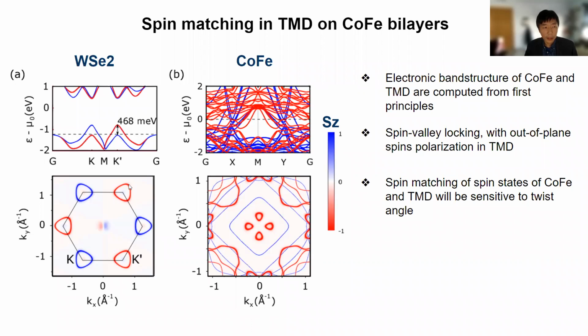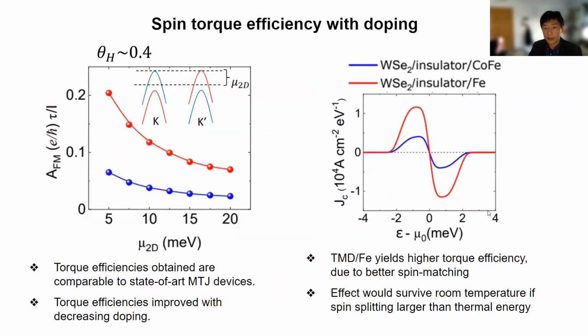And this is the Fermi surface of this TMD, and you can see that indeed the kappa and kappa prime valleys have opposite spin. So here is the band structure of the cobalt iron. We see that the Fermi surface of this cobalt iron is very different compared to the TMD, and you can also observe that the majority and minority spin doesn't coincide with the two valleys. The matching between the spin states would therefore be very sensitive to the relative orientation between the TMD and the cobalt iron, and that will be something that we will look at in the next few slides.